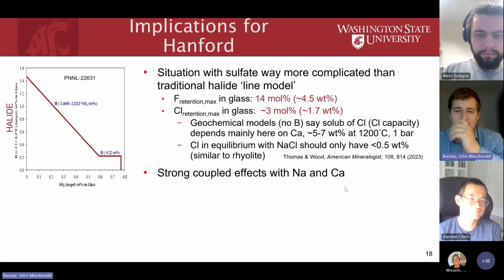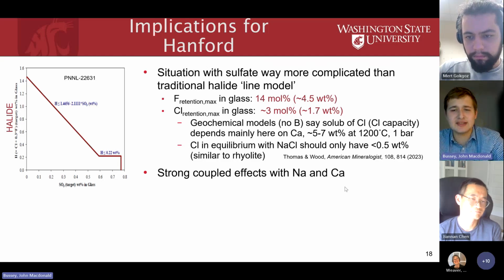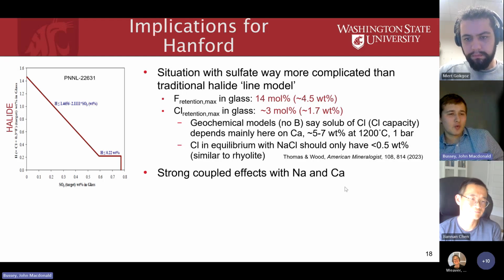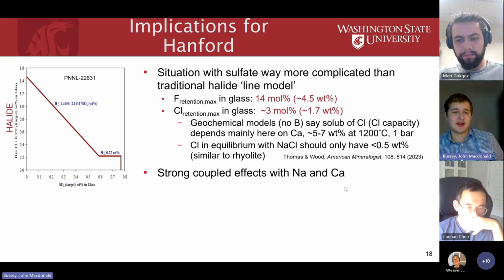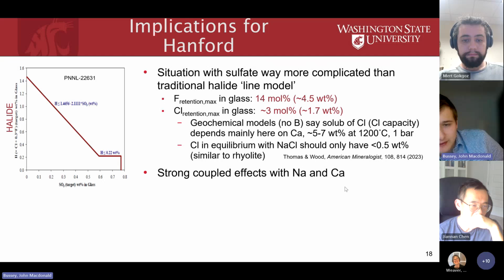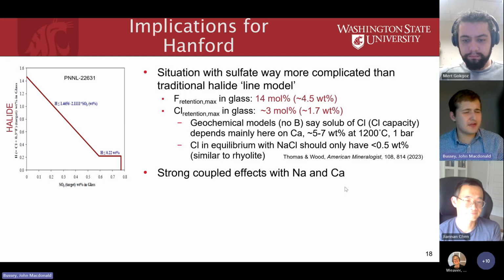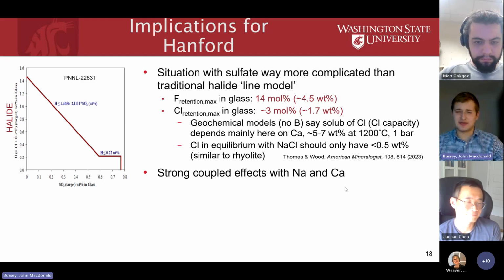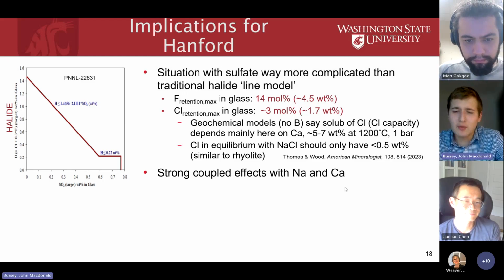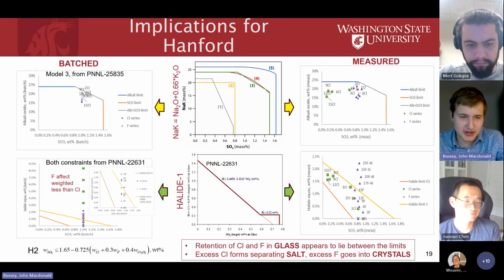The fluorine retention, again, was over 14 mole percent, up to almost nearly 5 weight percent just in the glass, plus durable crystals forming for at least a little bit longer. Whereas we found that the chlorine retention is very poor. We lost about 3 mole percent. So there's that. The other thing to note is that there's obviously a lot of effects with sodium and calcium, which was previously known, but it's good to know.